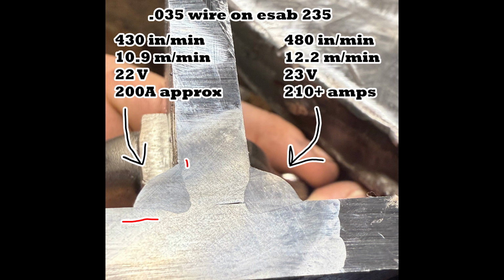Now on the right side, the 480 inches a minute, 23 volts, somewhere in the neighborhood of 210 plus output amps. The weld overall looks a lot better. Yes, there's a straight line on the right, however, that's into the plate. That's a decent fusion line. It broke down into the plate. The upright plate could be a little bit better on that area where it kind of slopes a little bit in towards the face, but this is, again, short circuit MIG. This is about the best that you're going to see on 3/8 plate.